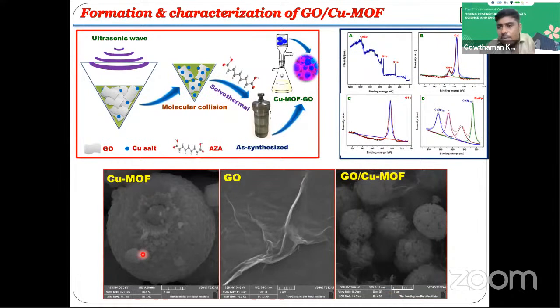When we take copper MOF alone, the size is very large, but when we react the copper MOF with graphene oxide, the size is controlled very well. See the difference in size: the size of copper MOF alone is large, while here it is very controlled. So this is a size-controlled synthesis of copper MOF. Graphene oxide layers control the size of the copper MOF.